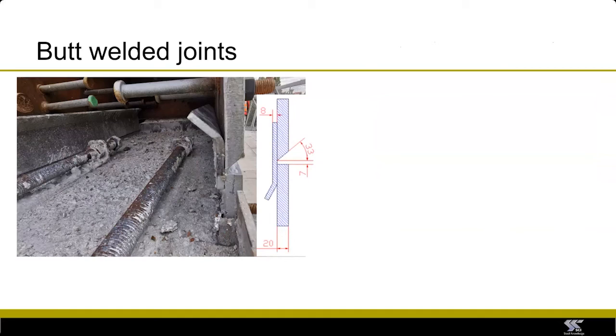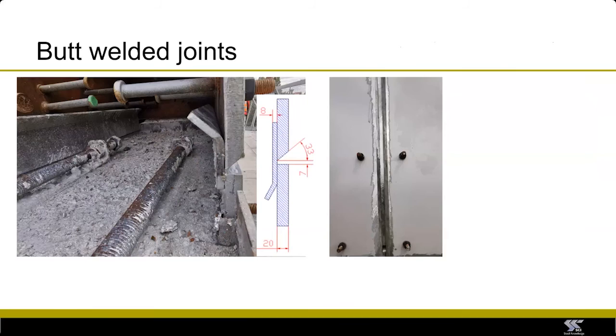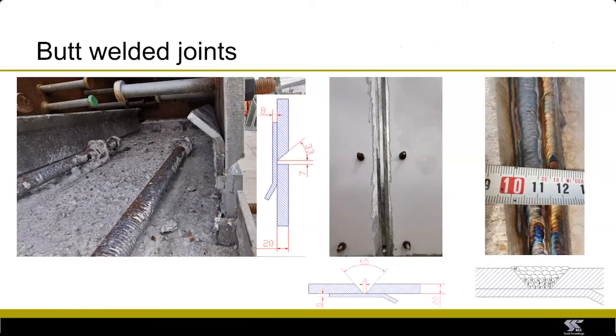Where the tolerances were most important was for the butt welded joints. You can see an example here of one that is a half V joint and another which was a V joint. Now the issue here is that if you end up with a gap that is too small, you have a problem. If you end up with a gap that is too large, you also have a problem in that you end up having to put too many weld runs in order to fill up the joint, and that takes up a lot of time, and it's a lot of weld metal and potentially deformations due to welding and so on.